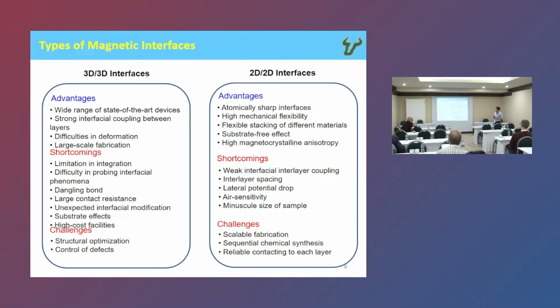And then a lot of the groups, when they synthesize materials, immediately report the properties. But when you transfer the material from one plate to the other plate, the properties can radically change. That's why when we work with magnetic TMD, we have to be very careful, because eventually you may not get really intrinsic magnetic properties from the sample. It could be an oxidized sample already, right?